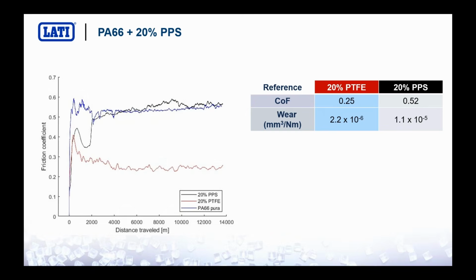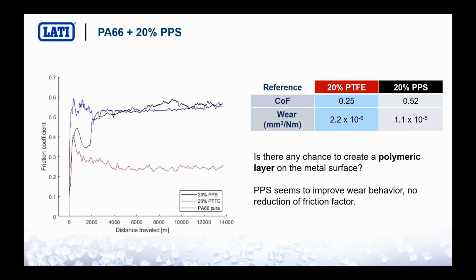We tested also PPS because in the literature we found some interesting results about the use of PPS as a self-lubricant additive in some particular compounds. But also in this case, we didn't see any improvement of the friction coefficient. While, from a wear factor point of view, we obtained slightly better results, 1.1 per 10 to -5, so a little bit better than an unfilled polyamide 66, but far from, for sure, the PTFE performances.